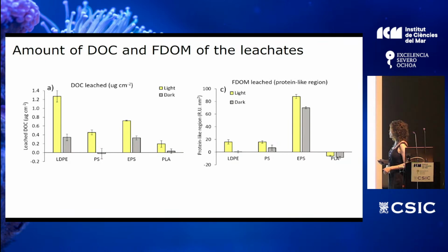And regarding the fluorescence, the one presenting the highest fluorescent DOM was the EPS, overall in the light in this case, and the others presented a small fluorescence. And the PLA, the biodegradable, showed negative values, probably because it absorbed the fluorescent material that could be present in the seawater.